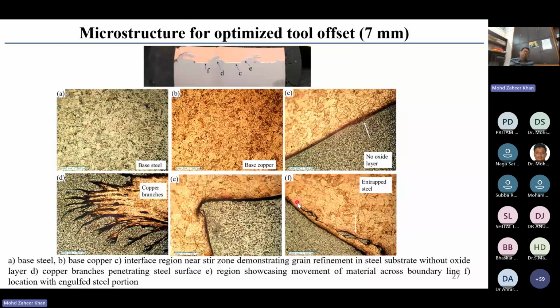This is the macrograph and a micrograph of the cladded layer. So several passes with the 7 mm tool offset were produced. And as you can see, this is a substrate. On top of it is copper. During the friction stir welding process, you can see there is an interlocking that is taking place. Of course, there is a metallurgical bond as well as interlocking that has taken place between the substrate and the clad material. And this interlocking further enhanced the strength that was achieved by the metallurgical bonding. At a magnified level, you can see that such intricate bonding or mechanical locking has taken place between the substrate and the clad material, ensuring that the clad material is firmly anchored on the top of the substrate material.